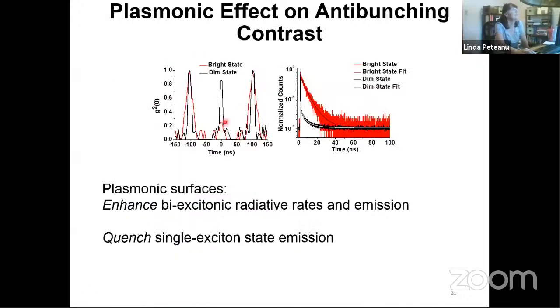Finally, we can do the same experiment comparing gold to glass, and again thresholding bright versus dim. And once again, we find that there is a decrease in the anti-bunching contrast on gold, which signifies that we have enhanced the biexcitonic emission compared to single excitonic emission. And once again, if we look at the lifetimes, what we see is that the lifetime of the biexciton state has gotten even shorter. So we presume from this that the plasmonic surface is enhancing the biexcitonic emission because it's increasing its radiative rate and making it competitive with the factors that will cause it to be quenched, whereas the single exciton state is quenched by energy transfer to the surface.